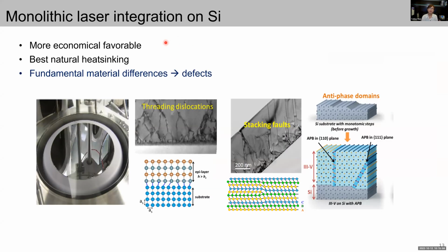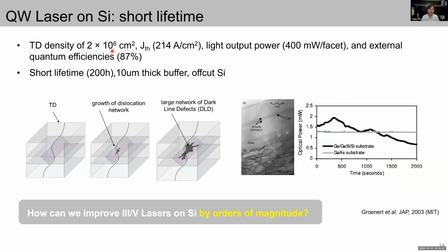So considering the III-V substrate cost, monolithic integration through direct epitaxial growth is a more economically favorable option, and it can also provide the best natural heat sinking for laser operation. However, the fundamental material difference between the III-V and silicon during the epitaxial growth can generate a high density of crystalline defects, including primarily threading dislocations, stacking faults, and antiphase domains. So these dislocations have associated trap states that act as non-radiative recombination centers that tend to gather an atmosphere of point defects that promote further growth of dislocation networks, and finally, this large network of dark line defects severely degrades the device performance and shortens the lifetime.